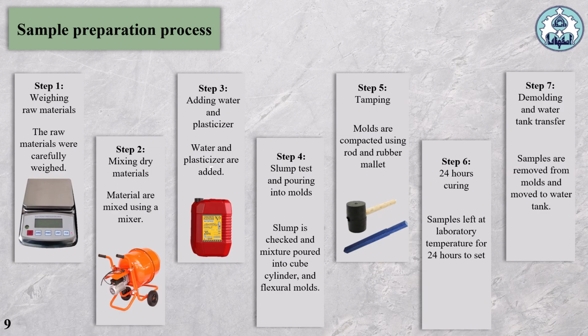The workability of the fresh concrete was checked using the slump test. The target slump was approximately 12 cm, ensuring the mixture was suitable for molding. The mixture was poured into cubes, cylinders, and flexural molds. The molds were compacted using a rod and rubber mallet to remove air pockets. Samples were left at laboratory temperature for 24 hours to set. Finally, the specimens were demolded and transferred to a water tank for curing.